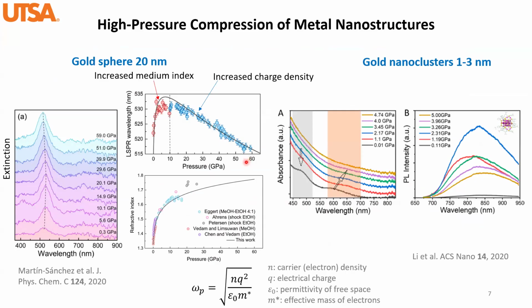Previously, there were only about 20 to 30 papers published in this field about metal nanostructures at high pressures, and I just picked two of the most representative ones. On the left side, we have authors working on gold nanospheres, and they were detecting the localized surface plasmon resonance as a function of pressure. In this figure, they plot the localized surface plasmon resonance as a function of high pressure. They saw first a redshift that is attributed to the increased medium refractive index. Then above 10 gigapascals, they started to see an increased charge density kicking in, which causes a blue shift of the localized surface plasmon resonance.